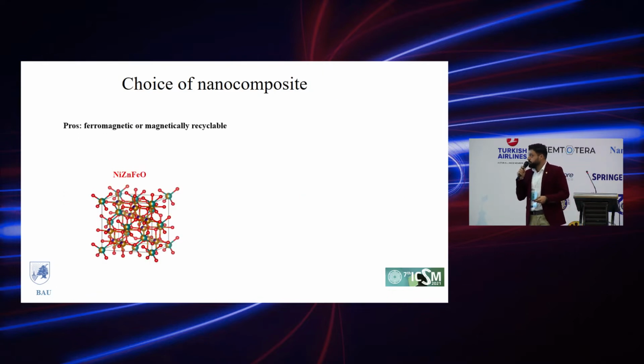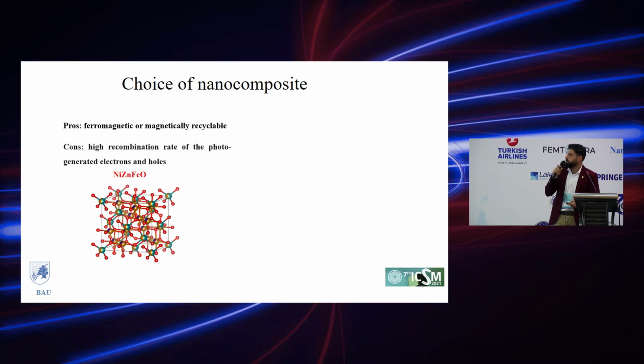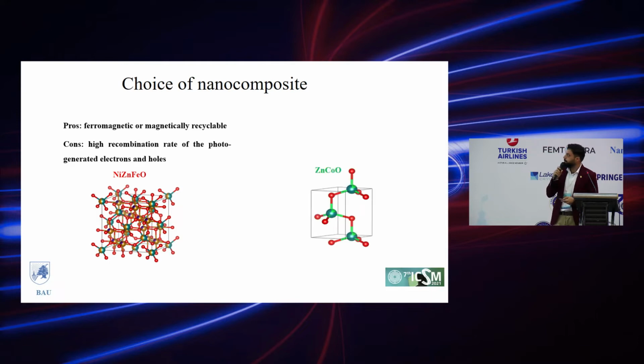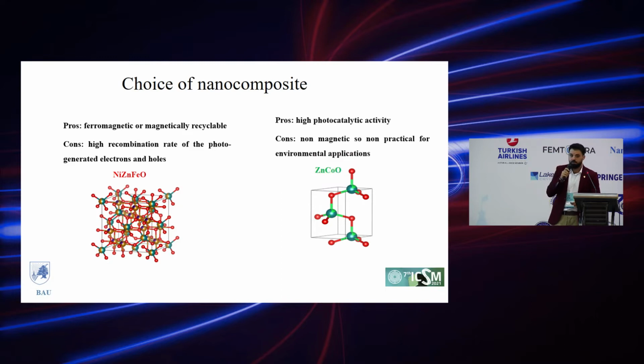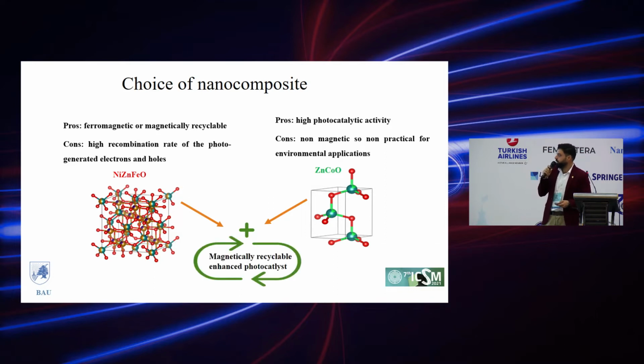Choice of the nanocomposite. So as I mentioned, one of the pros of nickel-zinc ferrite is that it's ferromagnetic, or magnetically recyclable. And this is very important in photocatalysis because we need to recover the photocatalyst by applying an external magnetic field. So this is the advantage of the ferrite. However, it has a high recombination rate of the photo-generated electrons and holes, which reduces its photocatalytic activity. Zinc cobalt oxide has high photocatalytic activity, but it's non-magnetic, so it's not practical for environmental applications. We aim, by combining these two nanoparticles, to form a nanocomposite which is a magnetically recyclable, enhanced photocatalyst.